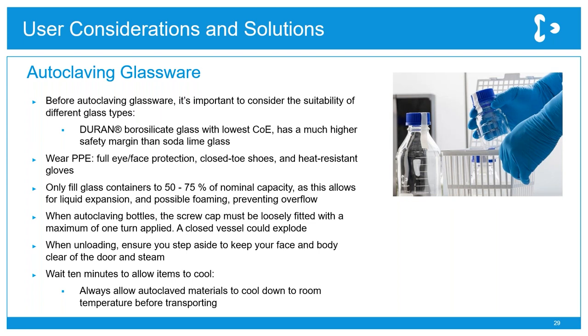It's also very important not to fully tighten the screw cap, because then the bottle can become pressurized and might explode. So always adequately loosen the cap to prevent the pressure from building up. When opening the autoclave door, be careful for steam because it gets hot, and also give the products time to cool before you handle them. Without adequate cooling, some liquids can boil when disturbed, and there's a safety issue there.